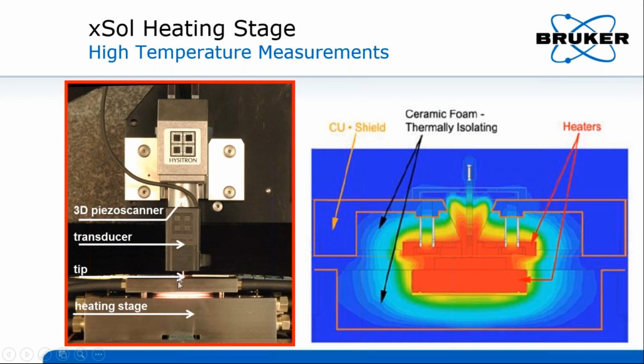The tip on the long shaft is designed to go into the chamber through the hole of the top heater. Therefore, the tip can be heated to the same temperature before going into contact with the sample surface. Of course, dynamic testing capacities are also available. On the other hand, no glue is needed since the heaters are designed to clamp the sample. It is a significant advantage because glue could be a big problem, especially at very high temperature.